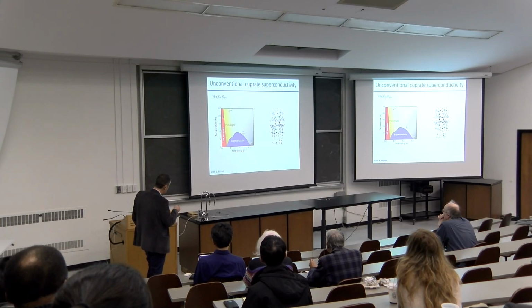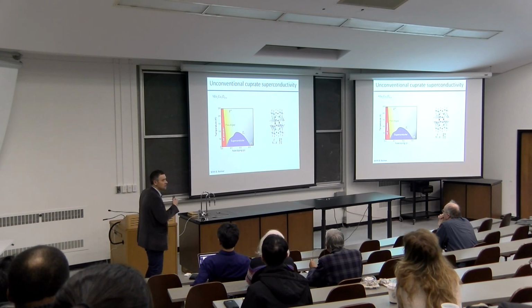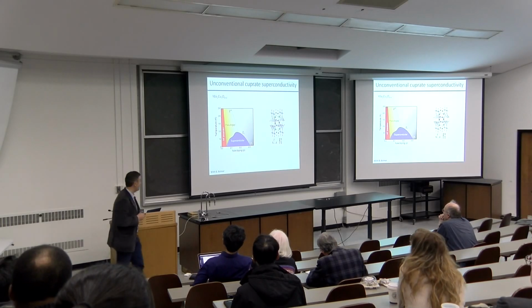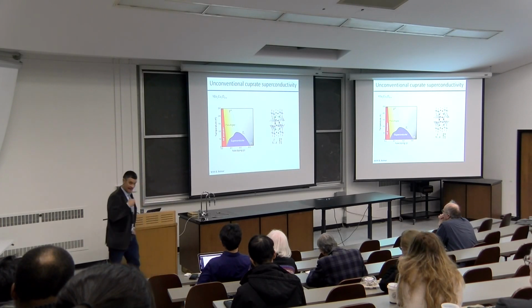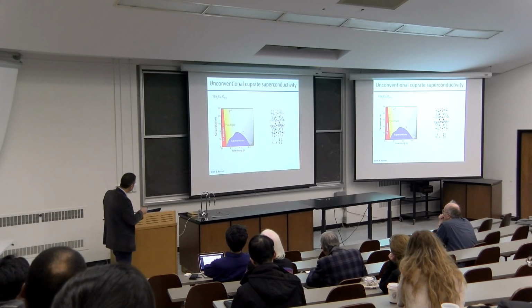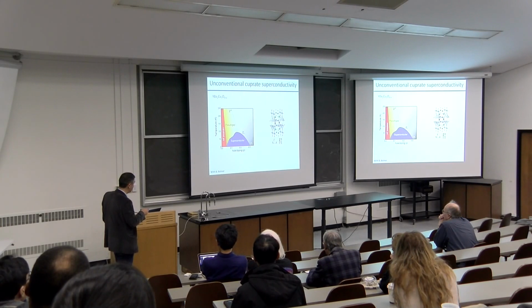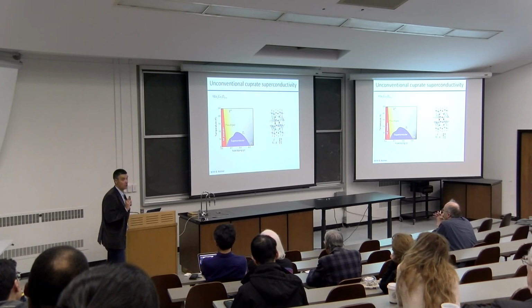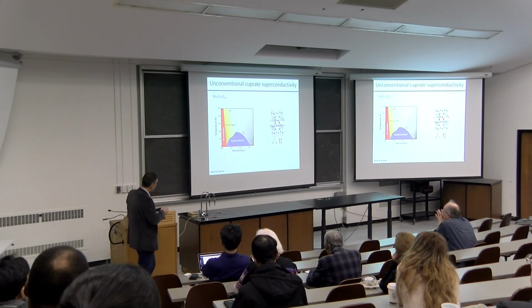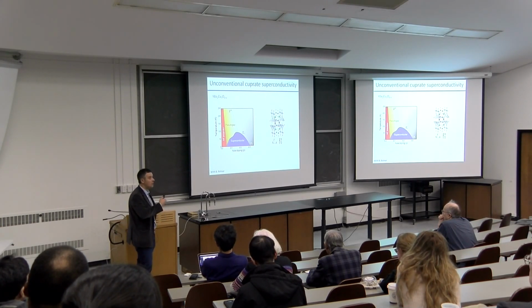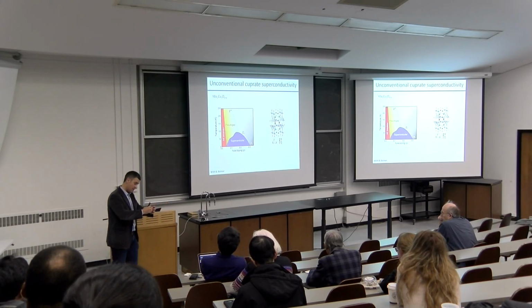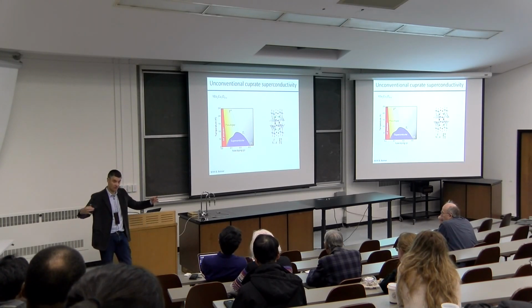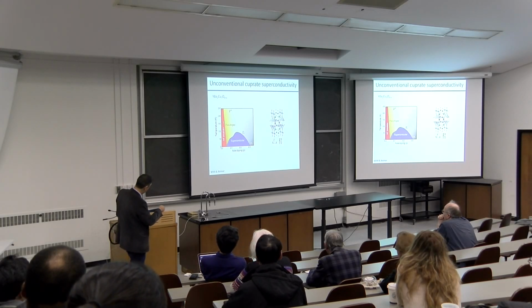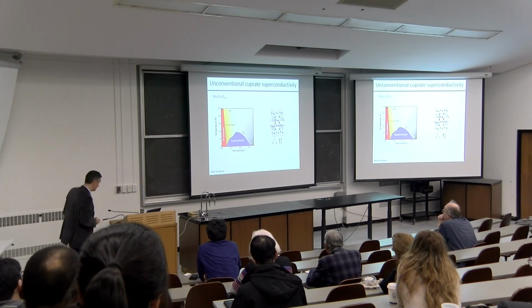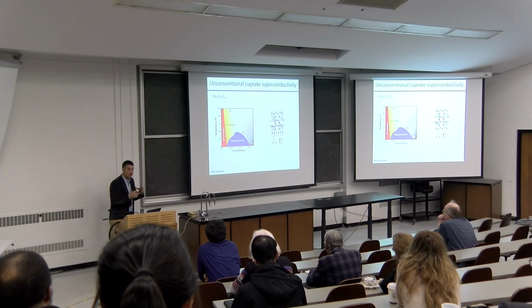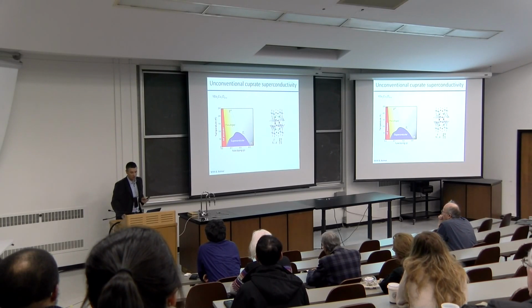There have been a lot of studies, and there's this mysterious phase that I will be discussing, in which some features appear to be those of a superconductor, including some optical spectra, some electronic spectra. This is why it is called the pseudo-gap phase. It has a gap that kind of looks like the superconducting gap, except that the system is not superconducting. There are many features here that reveal the proximity of this phase to the superconducting state. There's a lot of discussion of whether this pseudo-gap phase is basically a superconducting state already, in which, however, the correlation length of the superconducting state is not long enough to create a fully formed superconductor. Some people call this a phase-incoherent superconductor. So some people will argue that this pseudo-gap phase is basically a failed room temperature superconductor. And so this is exactly where we would like to be playing around with our phononics to see whether we can teach this system to act properly.